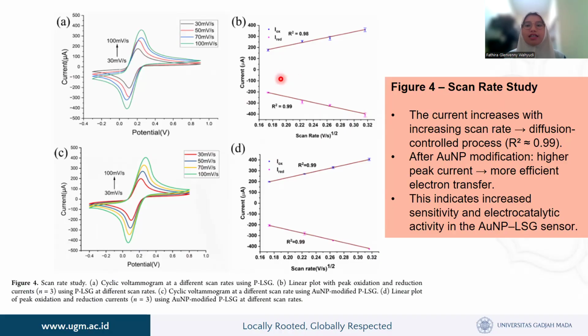And with B, linear graph between peak oxidation current and reduction current against the square root of the scan rate. The R square value is 0.98 and 0.99, this one and this one, indicating a strong linear relationship, a diffusion-controlled process. And with C, CV after modification with AuNP or gold nanoparticles shows a significant increase in peak current, indicating higher electrocatalytic activity and increased conductivity.